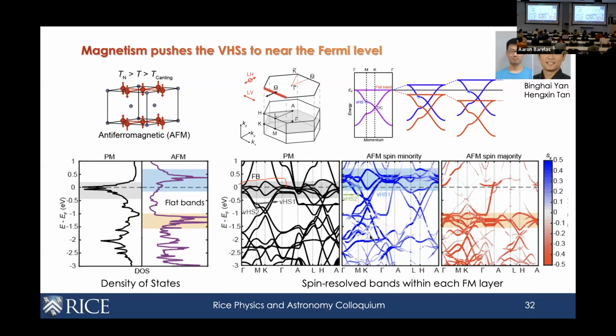That's a great question. For iron germanium, the correlation is not negligible. If we compare our measured dispersions with this band picture, there's not a one-to-one matching. So this is only providing some intuitive, qualitative overall picture of what these features do. I don't think it's a very accurate prediction of what the band structure would look like given a magnetic Kagome system. The second thing is that we also recently measured iron tin, which is another magnetic Kagome system, but that one does not have a charge density wave. So you may ask, yes, that's exactly the point. There, when the bands split, somehow the Van Hove singularity gets destroyed in that process because of hybridization with other bands. So in that system, we don't observe Van Hove singularities, even if there's magnetic order. In this system, it looks like it is preserved in this process.